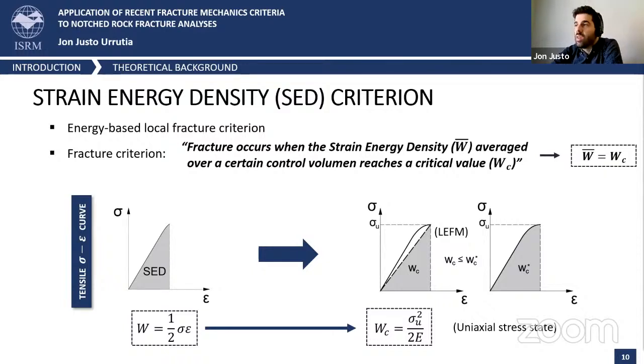So moving now to the strain energy density criterion. This is an energy-based local fracture criterion, and basically it states that fracture occurs when the strain energy density averaged over a certain control volume reaches a critical value. The strain energy density can be defined as the area under the tensile stress-strain curve. So assuming a perfectly linear behavior of rock, the critical value of the strain energy density can be defined as the area defined by the triangle.